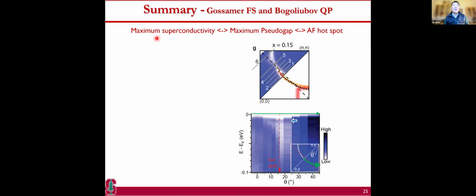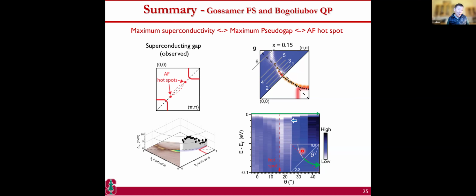You can see that there's a maximum superconductivity, the pseudogap, and the antiferromagnetic hotspot. They all happen at this time. The electron-doped system has the benefit that this hotspot is not at the antiferromagnetic zone boundary. Instead, it's going further away. So there's a non-monotonic behavior. Then we can differentiate away from other features such as the Van Hove singularity or the coupling to the B1g phonons and all that. So this, in a sense, is a cleaner system, although the Tc is lower in this system. Again, this all happened at the same time, and that's the first part of my story.